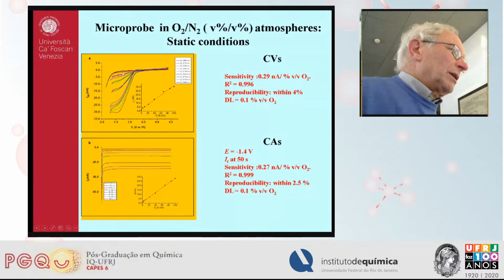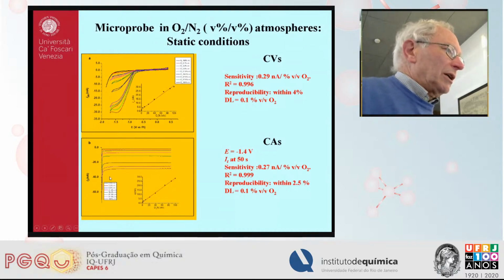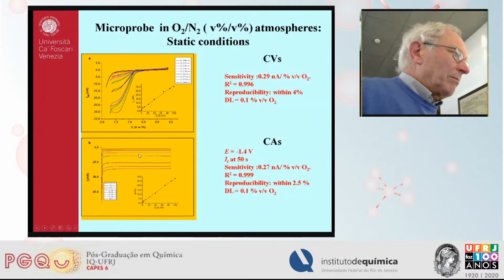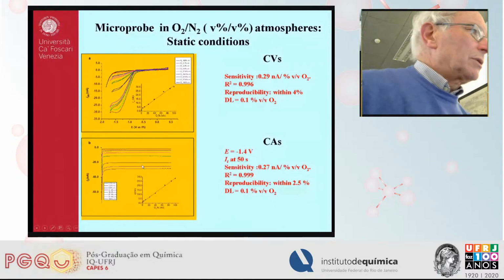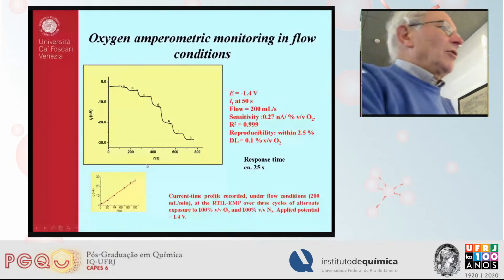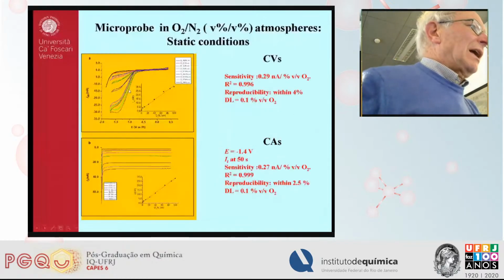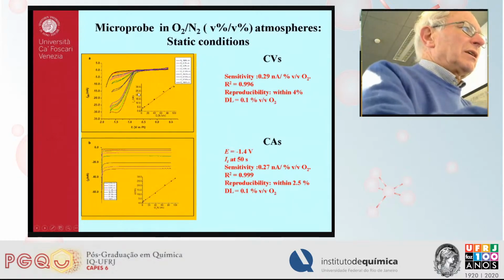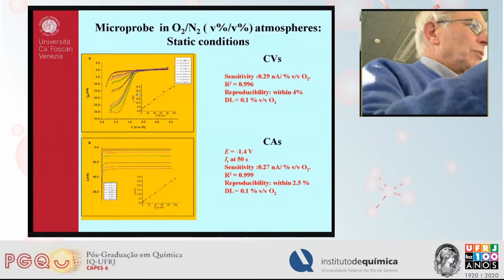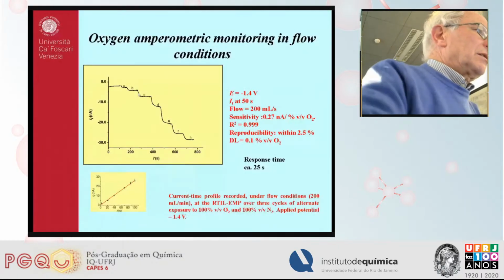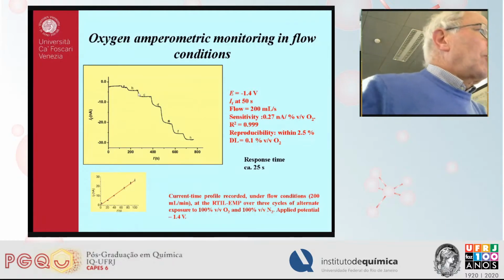So measurement can be performed quickly, in a much simpler way, by amperometry, by using chronoamperometry. In other words, by performing the potential step for a given amount of time. With a microelectrode, you can reach steady state in a short time. And again, the limiting current in this case is proportional to the percentage of oxygen in the mixture. To test the suitability of this system, because these measurements were performed under static conditions, which means we saturated the container with this mixture and then we made measurements, but the system works also under flow conditions.